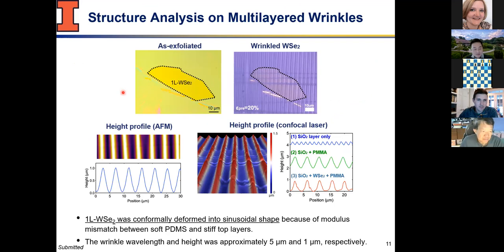So these look fancy and interesting conceptually, but as I said, it's lots of hard work of mechanical exfoliation. That's our one layer tungsten selenide that we exfoliate from bulk crystal. And then this substrate had a pre-stretch to it with a skin layer pre-made. So when you release the stretch, you get these wrinkle shapes. There are cracks that you see because of the Poisson effect: in the vertical direction, you have tension or compression by releasing the stretch in the X direction.